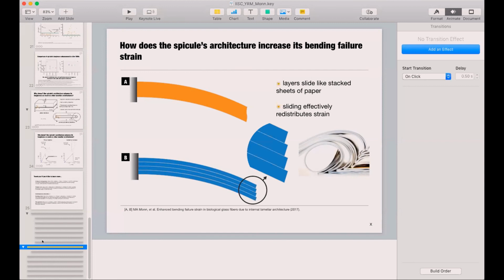Yes. To address the two points there, the first is about this idea of materials becoming less sensitive to flaws at the micro or nano scale. I think we can show that that is not the case by comparing the Euplectella spicules to the monolithic ones, the Tethya spicules. We don't really see that same kind of size effect as you'd expect out of work from a professor like Huajian Gao. But I do think that your point about suppression of defects is very important.